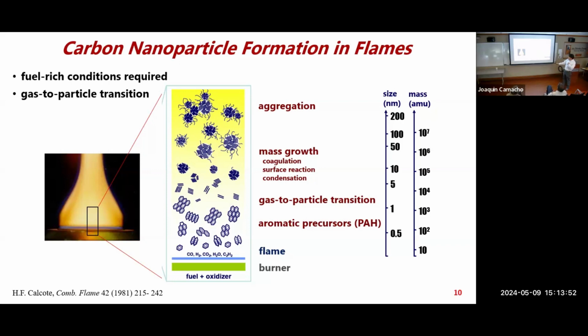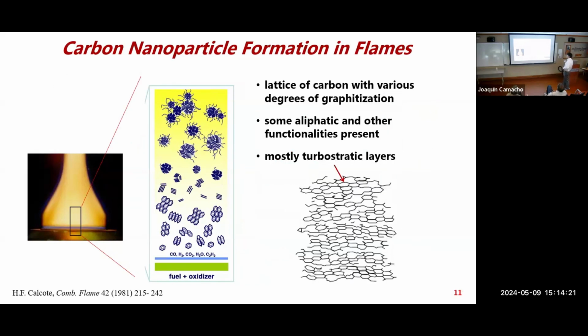If we look at this as a one-dimensional progression, which is hard to do in a real flame, but in a laboratory flame you can systematically study how, as you progress from the flame to formation of carbon soot precursors, you grow in size. Once you have this transition from the gas to the particle, there are a lot of processes where these particles grow. The structure of soot in traditional flames, at typical flame temperatures, is known to have some crystallinity, but not very sharp and not orderly crystalline structure. It is turbostratic, meaning it has some layers, some orientation to it, but it's not straight graphite layers.